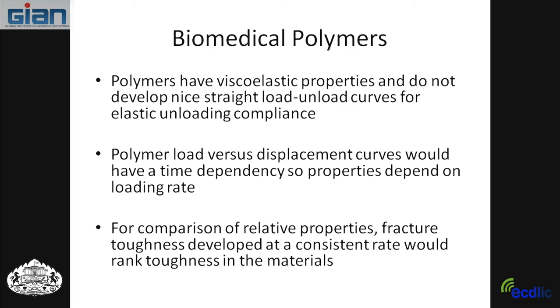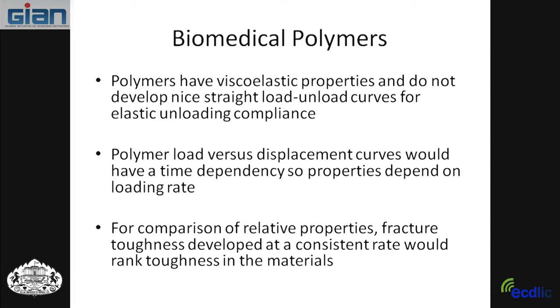We applied normalization to biomedical polymers. They have viscoelastic properties and don't develop nice load-unload curves for using elastic compliance, so we use normalization instead. Polymer loading being viscoelastic has time dependencies, so properties depend on the loading rate. However, if you do consistent loading rates, you can do a relative comparison of properties. Fracture toughness developed at a consistent rate would rank the toughness of the material.